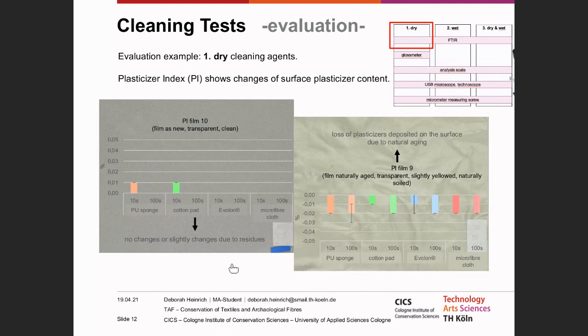The decrease in the plasticizer content of the surface, therefore, depends on the condition of the film. For cleaning, it should be considered whether the partial removal of superficial deposited plasticizer is preferable to a surface that may be sticky and attract further dirt. However, it should also be kept in mind that cleaning can promote the exudation of further plasticizer. In order not to base my results on one measurement only, I measured different aspects with the mentioned devices. From their interaction results the final evaluation.